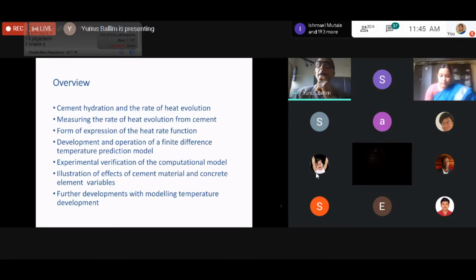And what I wanted to show you here are really the dominant crystal forms of cement. There are these very large tricalcium silicate crystals, angular, well developed. You can see the angled structures. And then there are these more rounded nodular dicalcium silicate crystals. There's the interstitial matrix material, which is really the brownish stuff that you can see here, the tricalcium aluminate phases, and the whiter, lighter areas are the aluminoferrite phases. And those really form the four dominant crystal structures of cement.